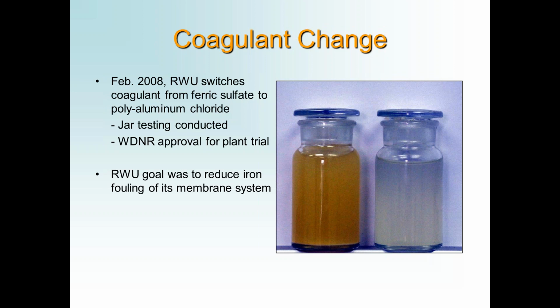It was strictly resulting from the fact that in our membrane plant, the fouling that was occurring on the membranes was due to iron carryover from the conventional treatment process, clogging the pores of the ultrafilters. Even though it's very low levels of iron, basically undetectable, there were still small particles of iron precipitate that you couldn't see that were clogging the pores on the membrane. So the idea here was to increase the efficiency of our membrane plant.